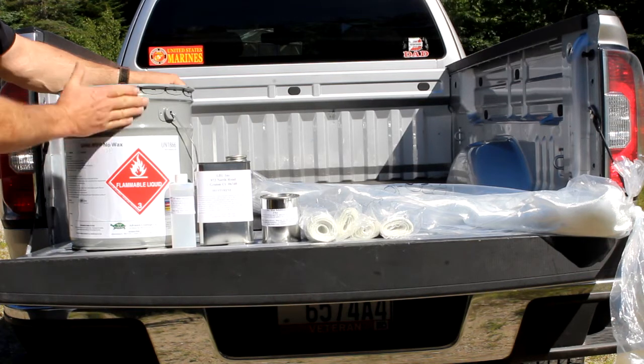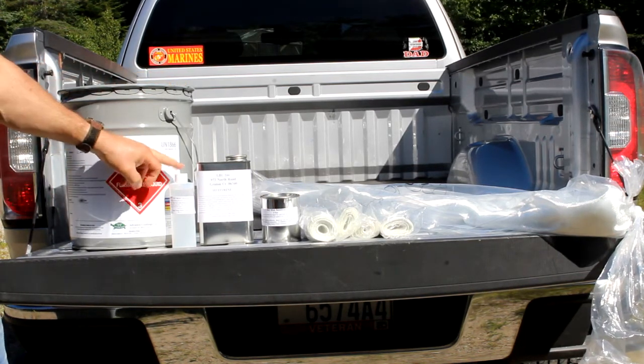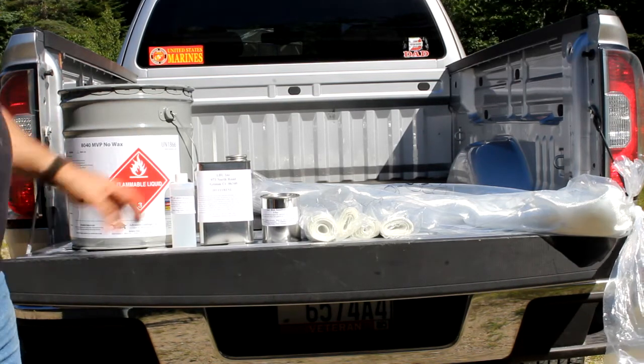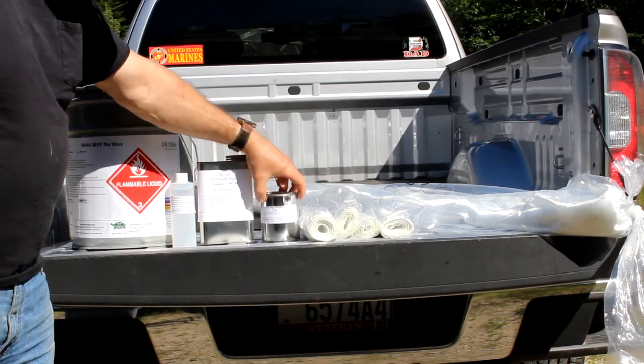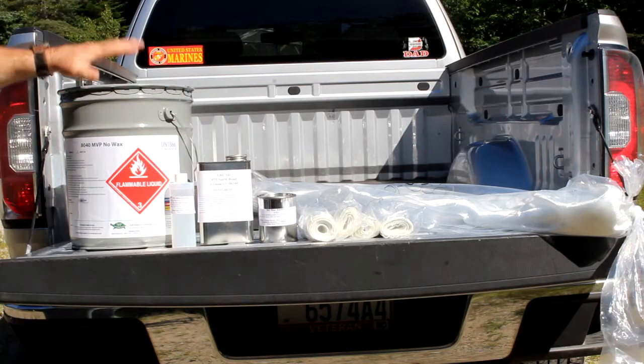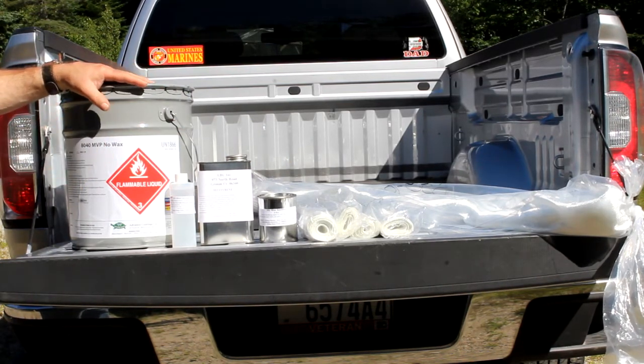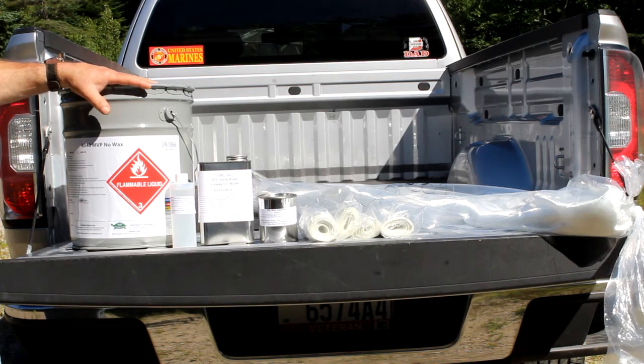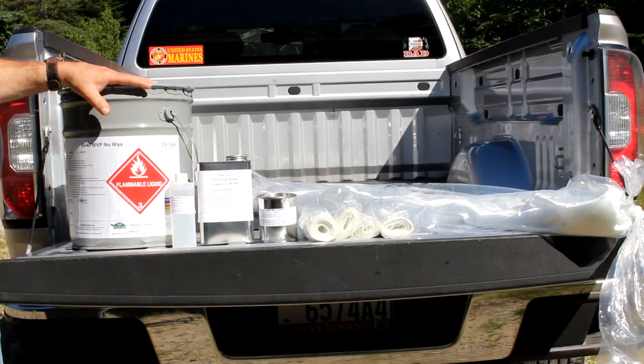build. This is 5 gallons of polyester resin and it comes with the MEKP catalyst. I also bought some styrene and some wax additive. The polyester comes without any wax in it. It's called laminating resin, and that way I get better adhesion between the plywood and the fiberglass and the resin, and also between any layers of fiberglass.